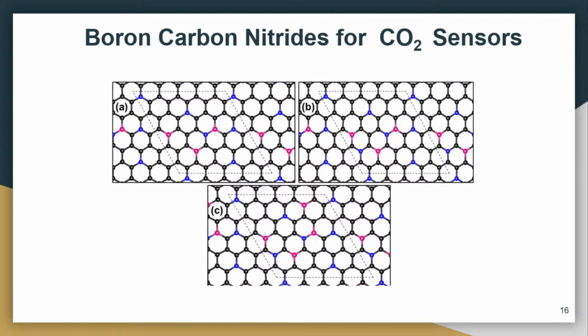This is the structure of what we are proposing. With respect to the change in temperature, different concentrations of boron and nitrogen are forming. So this is a model one, for a particular temperature, this is the structure, and this is another. When we are increasing the temperature, we increase the concentration of nitrogen, and we are getting some high nitrogen content. And here also the boron nitrogen content is increased. This is with respect to the different experimental setups. We did the BCN analysis, and with respect to the XPS analysis also, we proposed this type of structure with respect to the experimental findings.